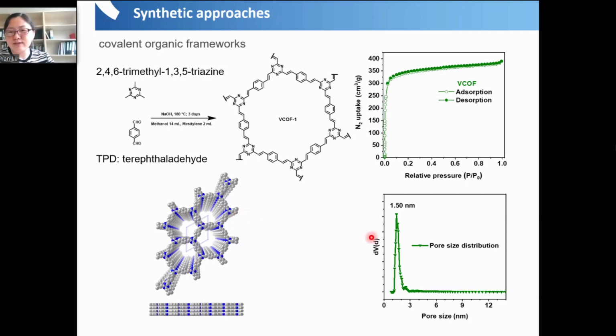In this case, you have this microporous material, and from the BET measurements, they have a specific surface area of more than 1,000 square meters per gram. And here, I just want to say I take this example from Professor Arnold Thomas. He's from TU Berlin. We work together, so we use this as a very nice additive for the all solid state battery system. And his group is also one of the pioneer groups from Germany working on such well-defined organic porous materials.